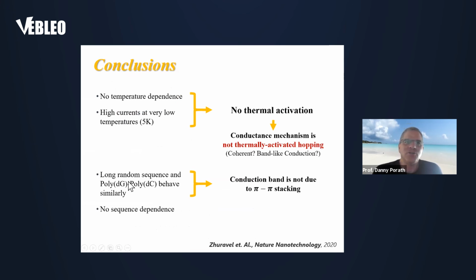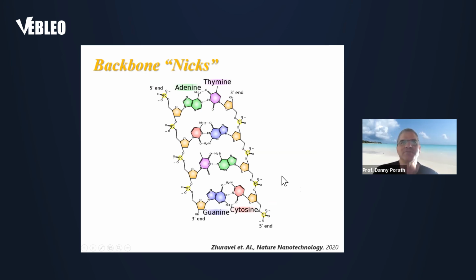And then the other observation is that the random sequence and the poly-G, poly-C behaved similarly, which means that it's probably not a conduction band due to pi-pi stacking, and that was hinting at the possibility that the backbone is transferring the current. That was very surprising for us, especially since the backbone is made of sigma bonds, but we went on to test it experimentally.